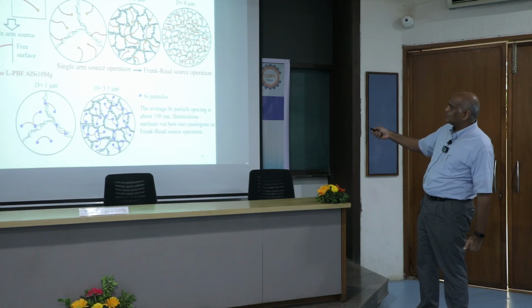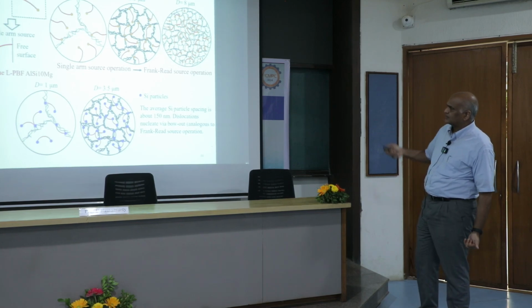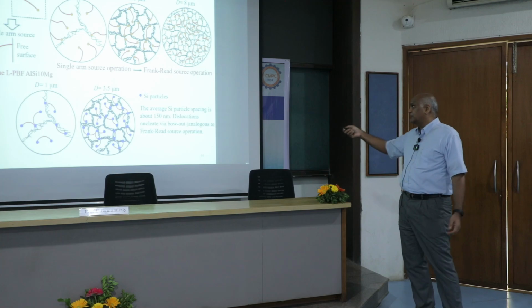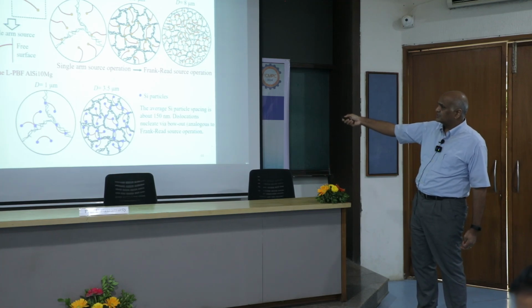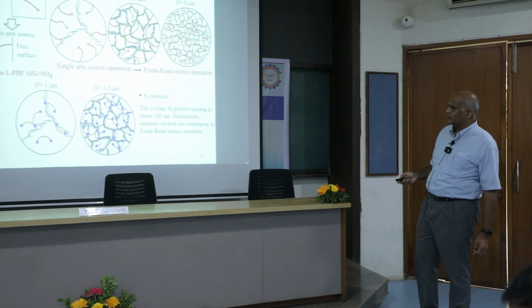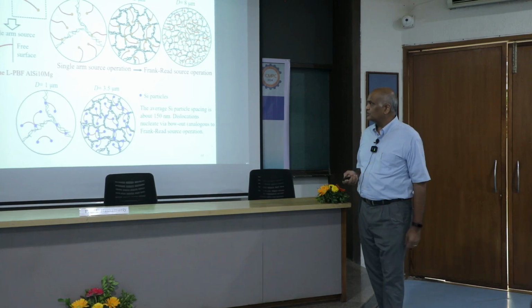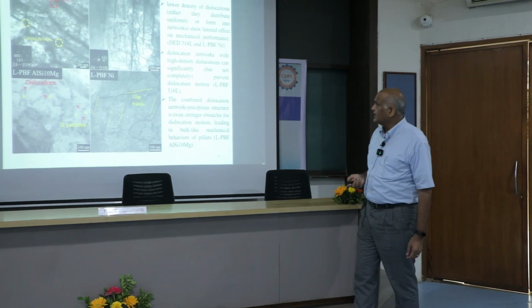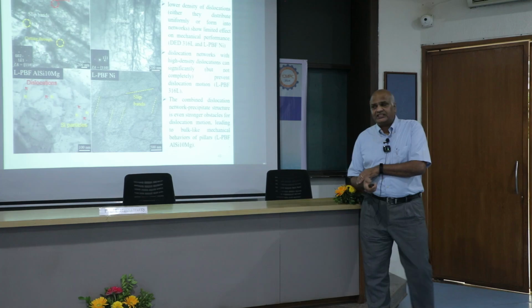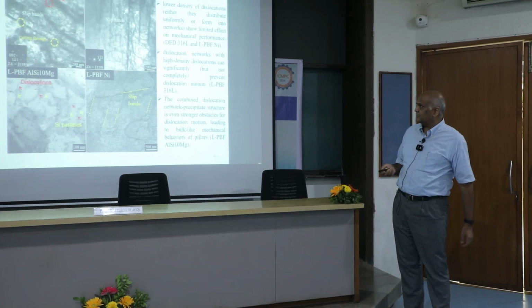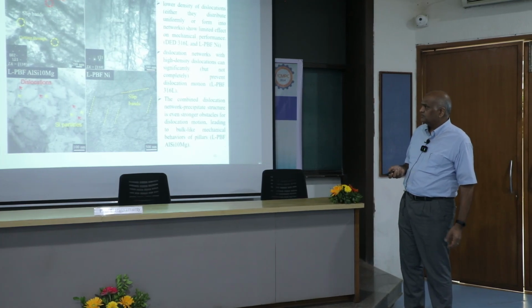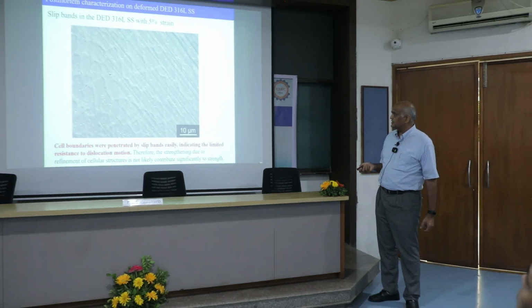But when you go to much larger diameter pillars, the full Frank-Read sources inside are operational, and they continue. So you get a bulk-like response here, whereas much higher strengthening when you have a much smaller diameter pillar. These are the kinds of mechanisms we can explain. Then we show through TEM what happens, the dislocations cutting through the cell walls and all that. We examine this on different materials.